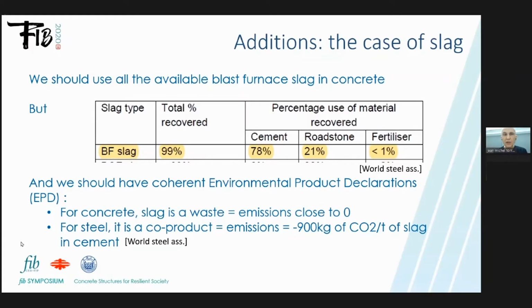And it means that if you add concrete and steel, something is missing, because in concrete we consider slag is zero emission, and in steel they consider it's a negative emission. So of course this situation is not correct, and it should evolve. And it means that, of course, in this case, slag will be less interesting from the environmental point of view. Nevertheless, it will be interesting, but less interesting.